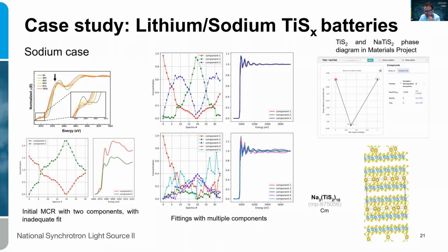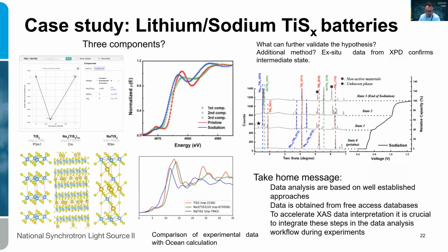And the interesting thing to see is that if you look at the phase diagram, there's actually a minimum in between the non-sodiated and the sodiated state. And this guy right here is the partially sodiated titanium sulfide. So let's see what we can do now. Again, we can pull the data for those three FEFF calculations, and they're actually in a very good match with the experimental data. It doesn't always work like this, but here we were just lucky.